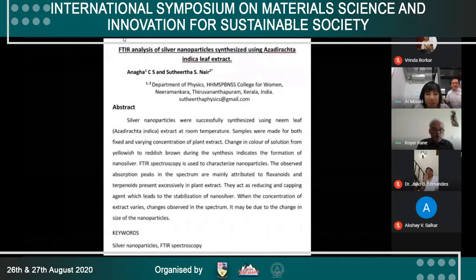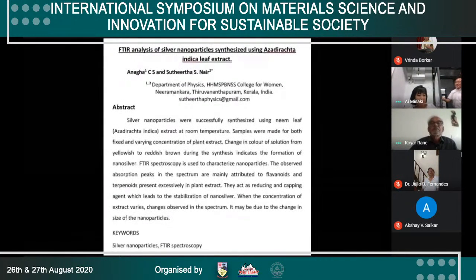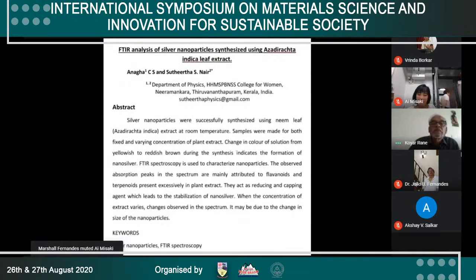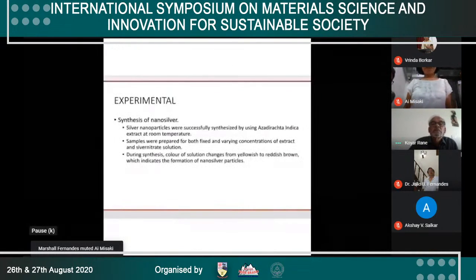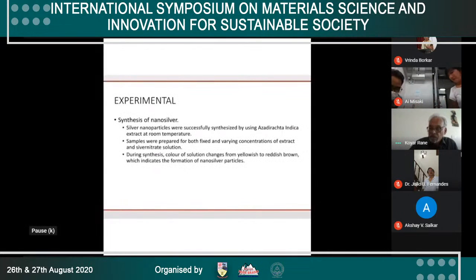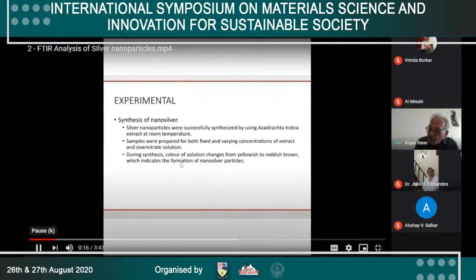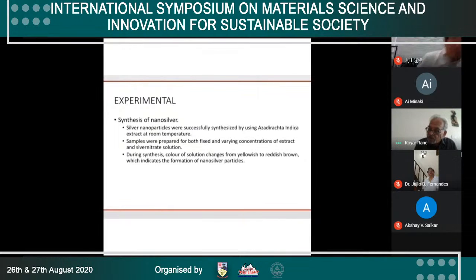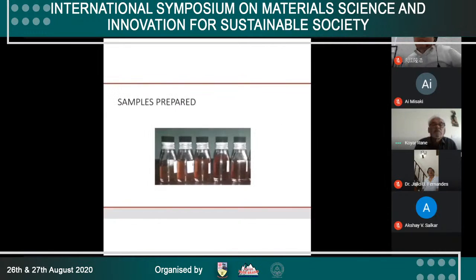Hello. FTIR analysis of silver nanoparticles synthesized using Azadirachta indica leaf extract. Silver nanoparticles were successfully synthesized using neem leaf, that is Azadirachta indica extract, at room temperature. Samples were made for both fixed and varying concentrations of extract and silver nitrate solution. During synthesis, the color of the solution changes from yellowish to reddish brown, which indicates the formation of nano-silver particles.